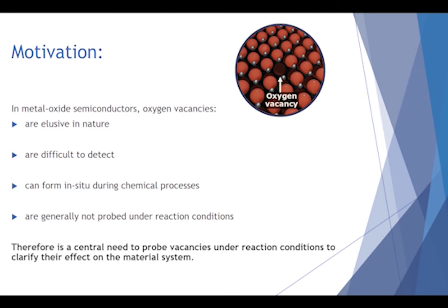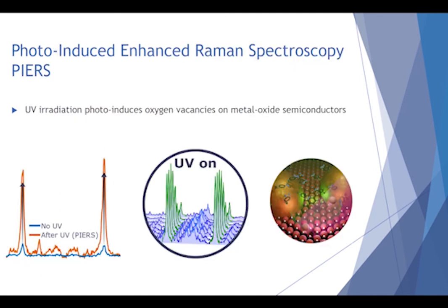And therefore, there's a central need to probe vacancies under reactive conditions to clarify their effect on the material system and how they affect different mechanisms. In this work, we probe for photo-induced oxygen vacancies on the surface of metal oxide semiconductors through a technique called PIERS, photo-induced enhanced Raman spectroscopy.